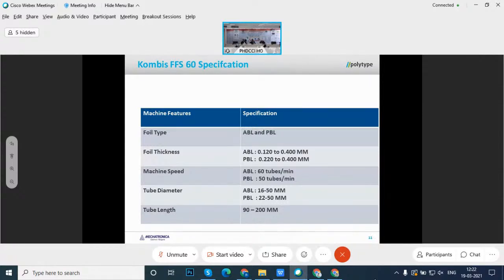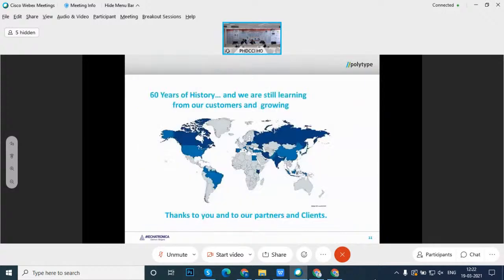Diameter, again a challenge. We also have one machine that is doing even a 10 millimeter tube. But this 10 millimeter tube is not very efficient because there is much more material, like the shoulder and cap, and inside there are only 2, 3, 5 milliliters of product. So this tube is more packaging material than product inside. But it could be made. And the length of 90 to 200 also could be reduced a bit. And that's it.